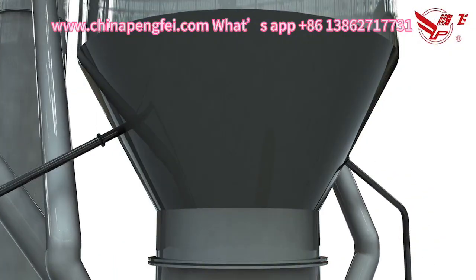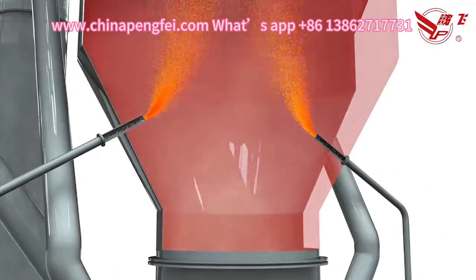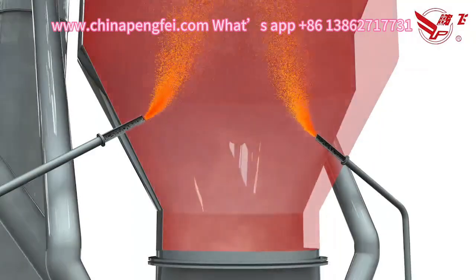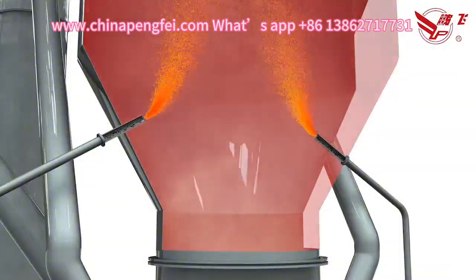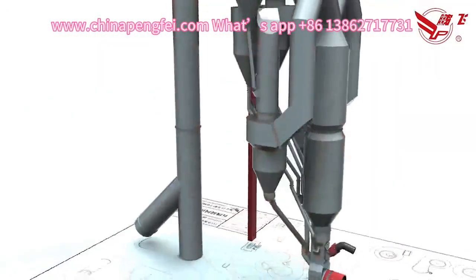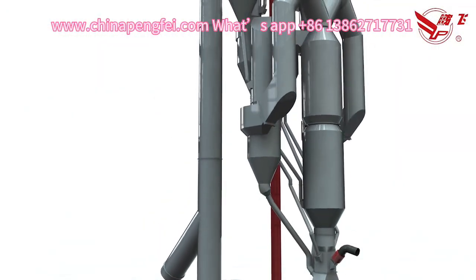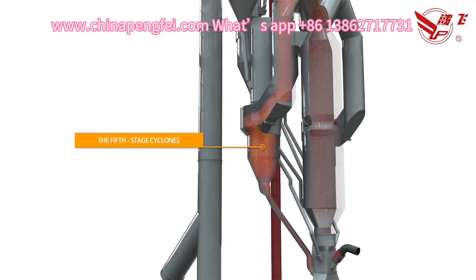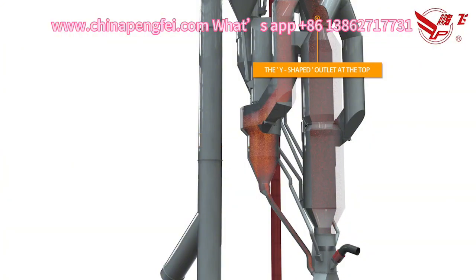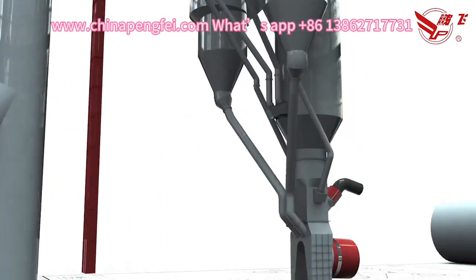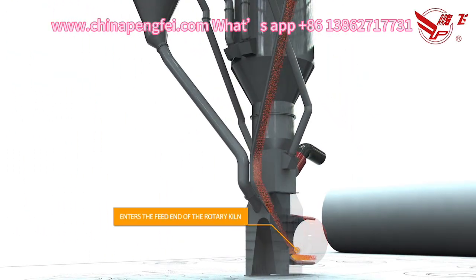There are multiple coal injection devices inside the pre-calciner. The pulverized coal is mixed with air and injected into the pre-calciner, where it heats the material inside the kiln together with the hot air from the kiln hood. Driven by the high-speed hot air, it moves upward and enters the fifth stage suspension preheater via the Y-shaped outlet at the top. At this point, over 92% of the carbonates have been decomposed. Finally, the material enters the feed end of the rotary kiln through the discharge pipe at the lower part, beginning the rotary kiln calcination process.